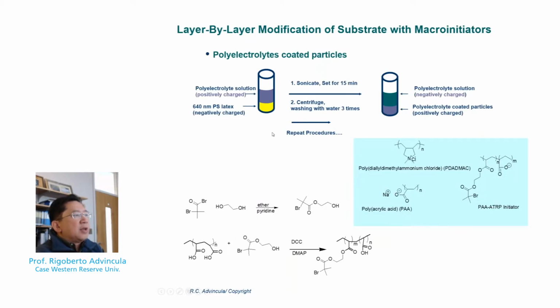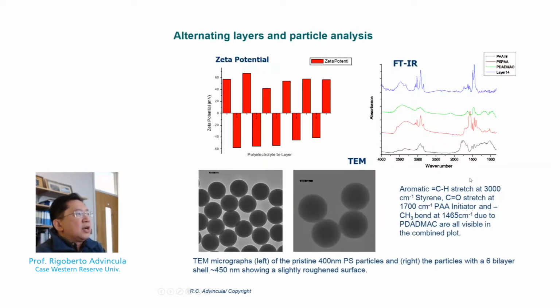Here's an example of the procedure and the chemistry that we use. So for example, we synthesize these macroinitiators based on a modified polyacrylic acid. This is an initiator for ATRP, or we call this PAA-ATRP. We first deposited alternately a negatively charged polyacrylic acid and a positively charged PDADMA on a particle surface, and then grafted the initiator followed by polymerization. This is shown here in this experiment. So originally, these polystyrene particles of about 400 nanometer diameter were coated with the polyelectrolytes to produce a layer-by-layer shell. This was followed by the zeta potential, which indicated the deposition of the negatively charged and the positively charged polymers, followed by the grafting of the initiator.